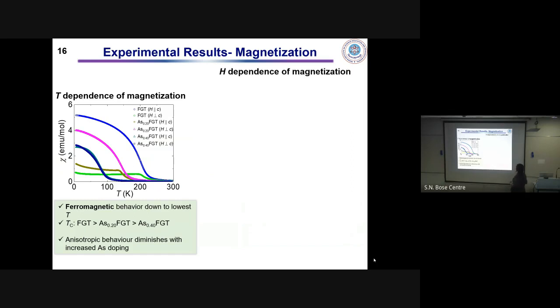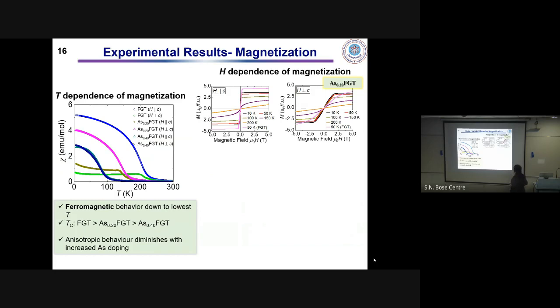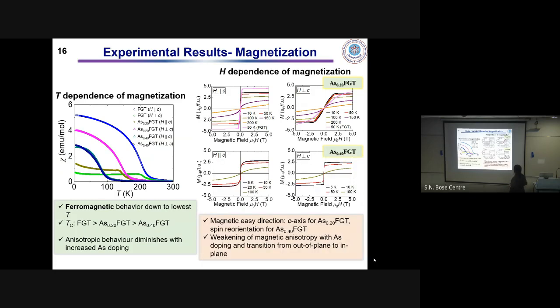And moving on to the field dependence of magnetization, we have seen for low arsenic doping that when the magnetic field is applied along the C-axis, the curve saturates at lower magnetic field, and when H is applied perpendicular to the C-axis, it's not saturating at this magnetic field. So it confirms again the magnetic direction is along the C-axis. However, there was a change in the case of the higher arsenic concentration sample, where we have observed a weakening of the magnetic anisotropy with arsenic doping, and there is a transition from the out of plane to the in plane direction.